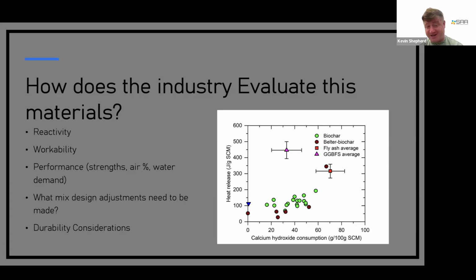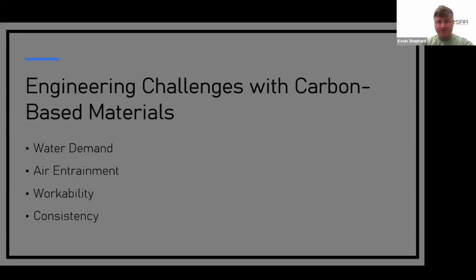Unless you want to use more plasticizer, which will reduce your water, right? But what mix design adjustments need to be made are the amount of water, the amount of chemicals that we're using, and the cement amount that we're using, the cement or sand. Durability considerations: a lot of the companies in our association are looking into it, but I don't see a lot of durability considerations around these materials. However that's tested, I think we need to prove that when this material goes into concrete, it will last the same as that old mix design that we are at. And I do see some issues in the field with this, so that's why I recognize it.